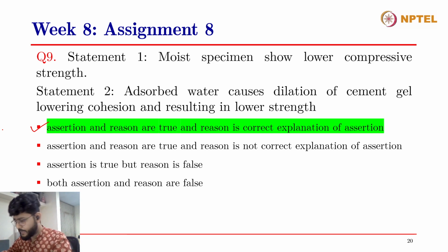if the concrete is kept dry for long, or you have obtained a concrete core from a structure, from a real structure, then they recommend you to cure it for some time before you actually test it, because curing will allow the water to get inside the concrete and dilate the cement gel and reduce the strength and achieve the same degree of saturation in all the concrete specimens that you're carrying out the tests on, right?